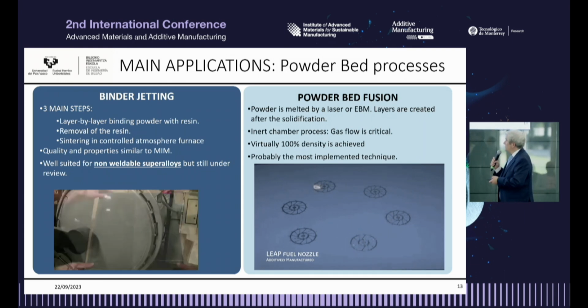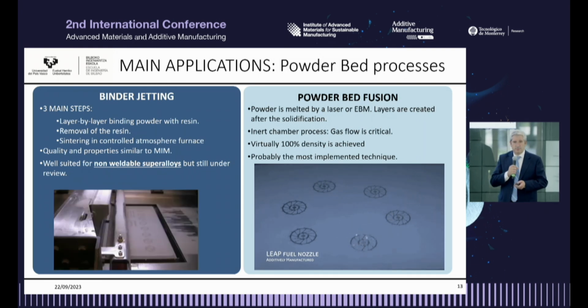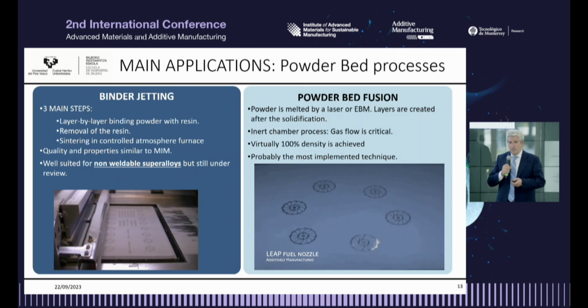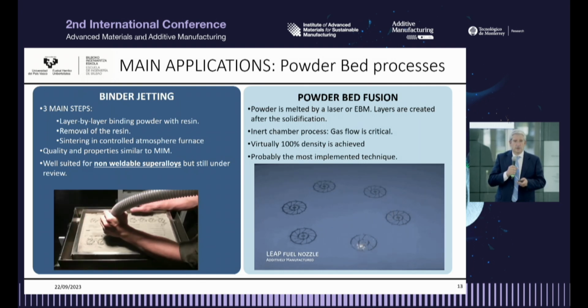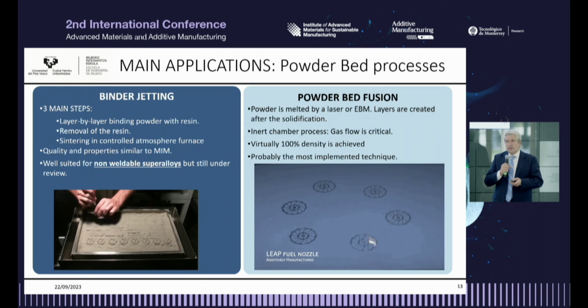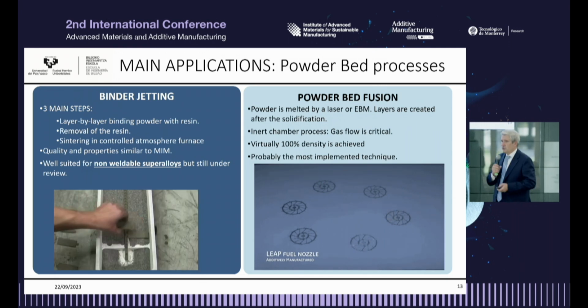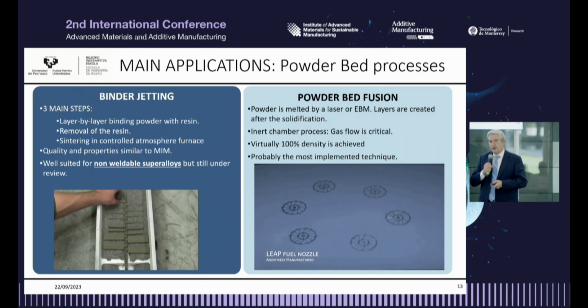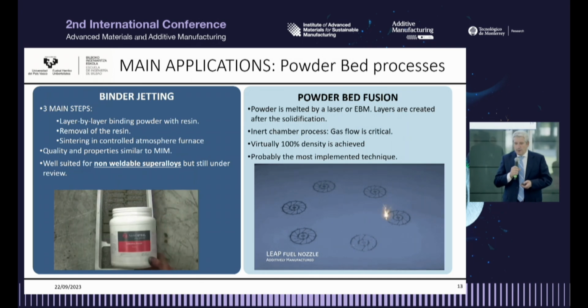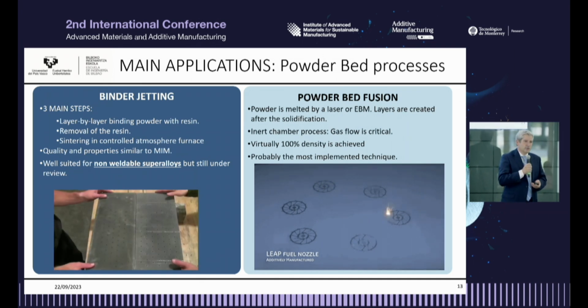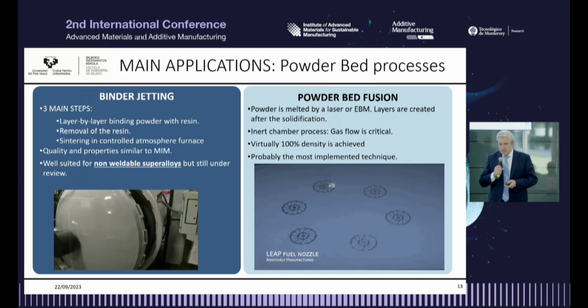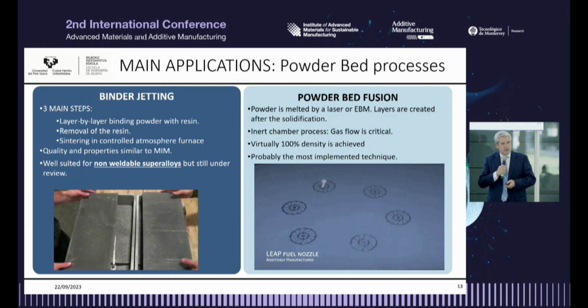And this process is now being evaluated by the aerospace industry for non-weldable superalloys, but it's still ongoing. So the main process in aerospace is powder bed fusion, where we use a laser or electron beam to melt powder and obtain a virtually 100% dense part. And it's probably the most implemented technique in aerospace by now.